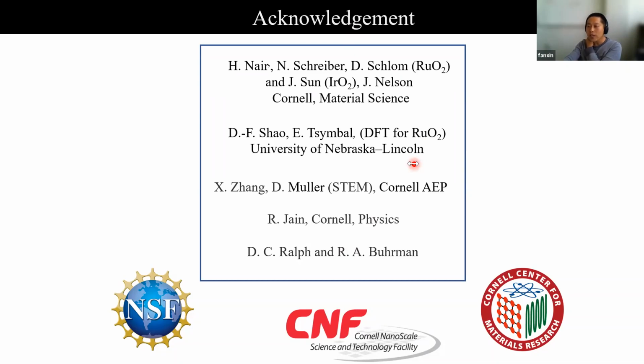While we're waiting for questions, I see there are 2 questions in the chat on Zoom. The first one is, can I expect out-of-plane spin current in amorphous state materials? Can you comment on this? My understanding is that it is most likely not possible. It has to be either a single crystal material, or we need magnetic ordering. If it's a magnetic material, then we can have out-of-plane anti-damping torques or extraordinary spin currents even for the polycrystalline material. But that may not necessarily exhibit the sort of angular dependence that we observe in this particular material.